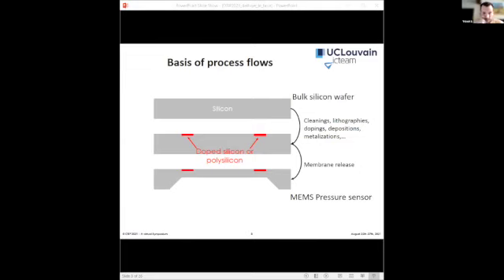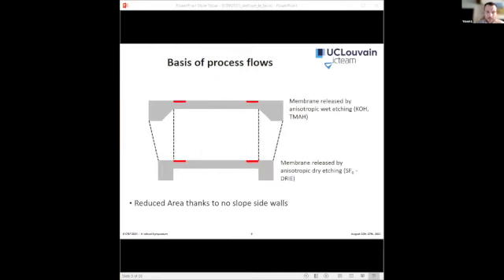So without going into details, they are manufactured inside microfabrication laboratories. We begin with, for example, a bulk silicon wafer, on which we apply a bunch of cleanings, lithographies, dopings, depositions, and so on, in order to obtain these doped silicon or polysilicon resistors on the front side of the wafer. And after that, we release the membrane by etching the substrate from the backside of the wafer. Different etching techniques exist. For example, we have anisotropic wet etching with KOH or TMAH, or anisotropic dry etching, for example, deep reactive ion etching with SF6. One of the main advantages of anisotropic dry etching is the almost no slope sidewalls, which allows, for example, reducing the area needed for the membrane release.